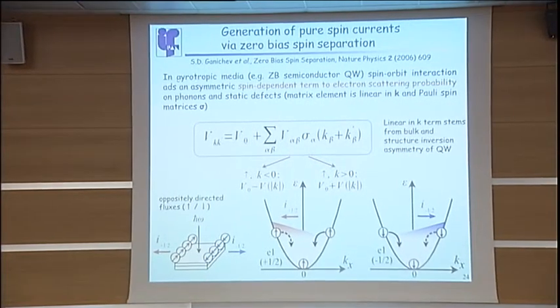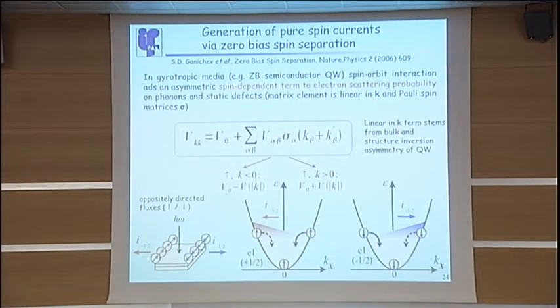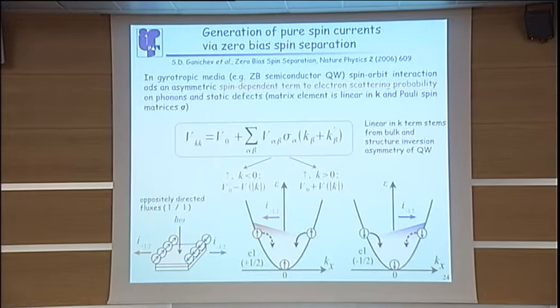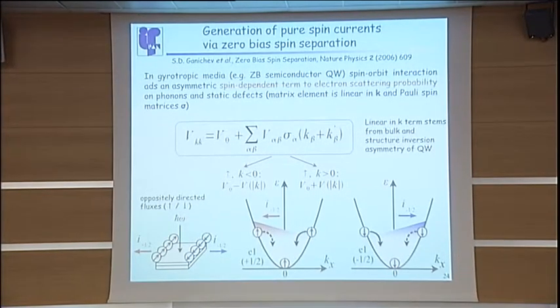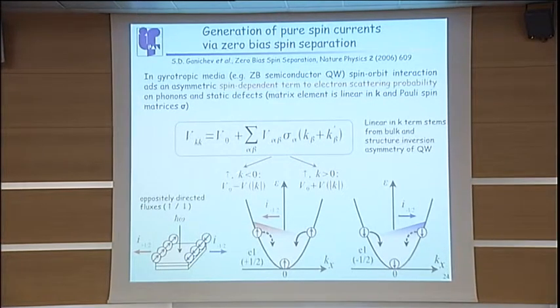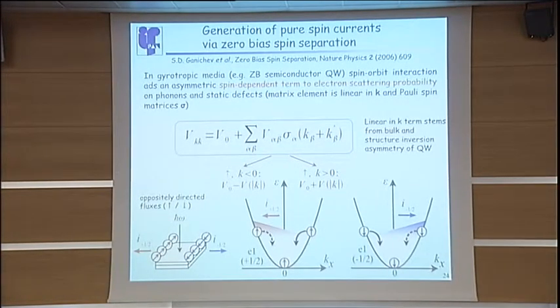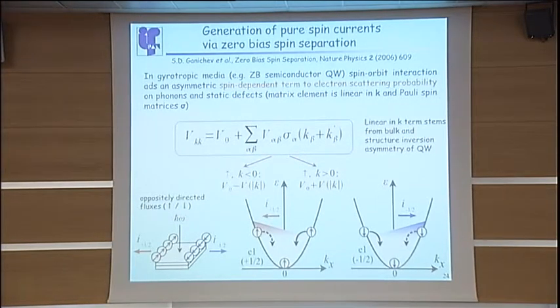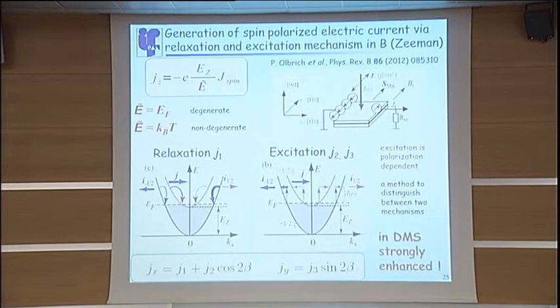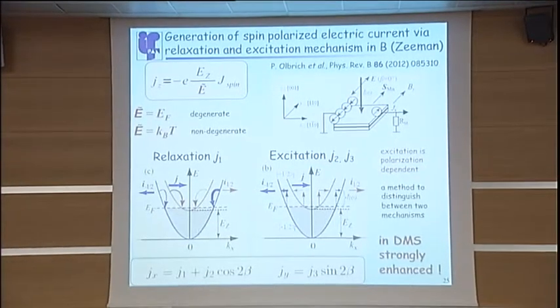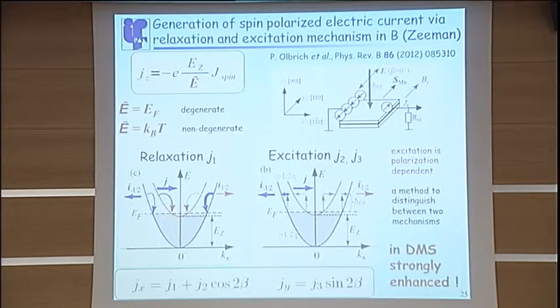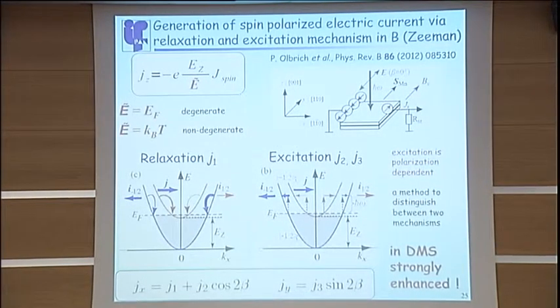He noticed that in gyrotropic media, spin orbit interaction adds an asymmetric, spin dependent term to the electron scattering probability. And of course, this is due to the bulk and structure inversion asymmetry. So now, depending on the sign of k, the potential is different. If you have, for instance, one direction of spin, then carriers are scattered more to the left, and for the other, more to the right. And if you have balance between those two, so you have the same occupation, you should have a pileup of spins with no electrical current. But if you apply a magnetic field, for instance an in-plane magnetic field, you produce the spin splitting, and then you produce an imbalance between those two currents, spin fluxes, sorry.